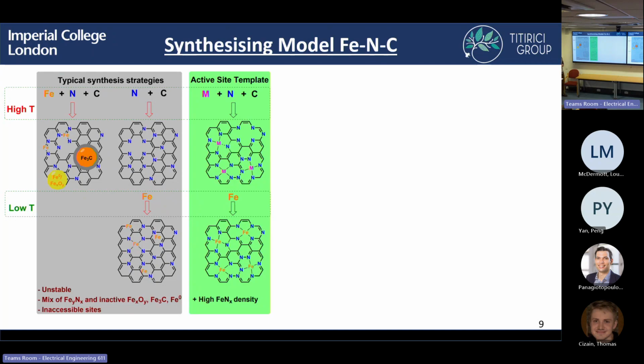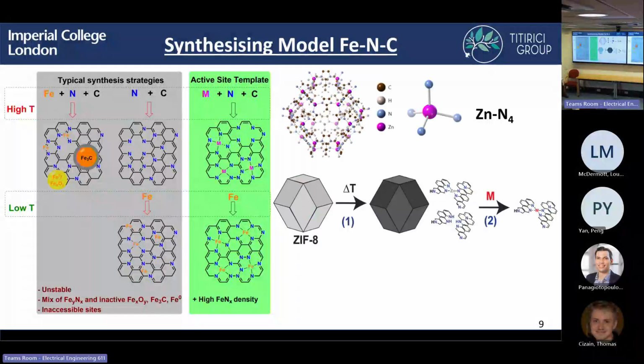And so what's been proposed in the last few years is to instead use this active site template method. You use a templating metal which doesn't undergo carbothermal reduction at high temperatures and can also form atomic species that coordinate to nitrogen. Then at low temperature, you replace this templating metal with iron, and you can end up with your atomically dispersed iron species. The most commonly used method to do this is using the precursor ZIF-8. This is a crystal which consists of zinc atoms coordinated to 4 nitrogens, and it's suitable as well in terms of carbothermal reduction, as it doesn't undergo these reactions at the typical pyrolysis temperatures. So you can take this ZIF-8 crystal structure, pyrolyze it, and then load your iron or your active metal at low temperature, and you can end up with purely atomically dispersed species.